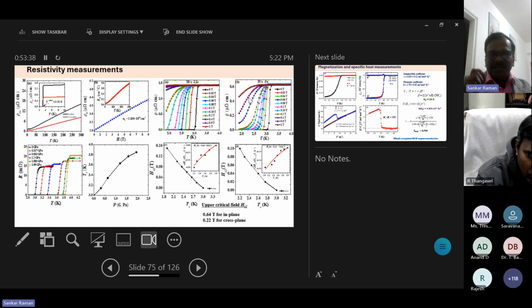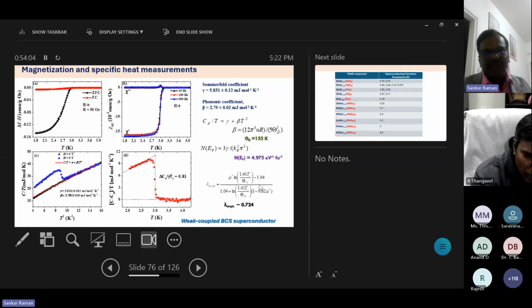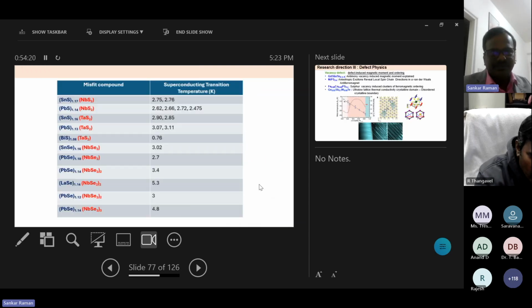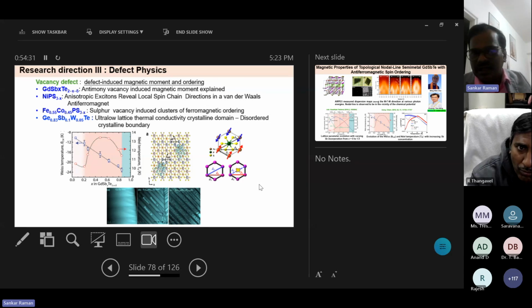We also applied different pressure to this material. We used 1.96 GPa from the SQUID, and we can enhance the Tc from 3K to almost 3.9K. The upper critical field is 0.64 Tesla in plane and 0.22 cross plane. That's why I say single crystals are very important for measuring the physical properties. We also checked the MH and MT data, clearly showing 3.2K, and the specific heat measurement. We also calculated the Sommerfeld coefficient, everything. It becomes a weak-coupled BCS superconductor. This is how we grew different kinds of misfit compounds using chemical vapor transport, also showing the superconducting transition. Maybe Thangavel is okay, or I can continue.